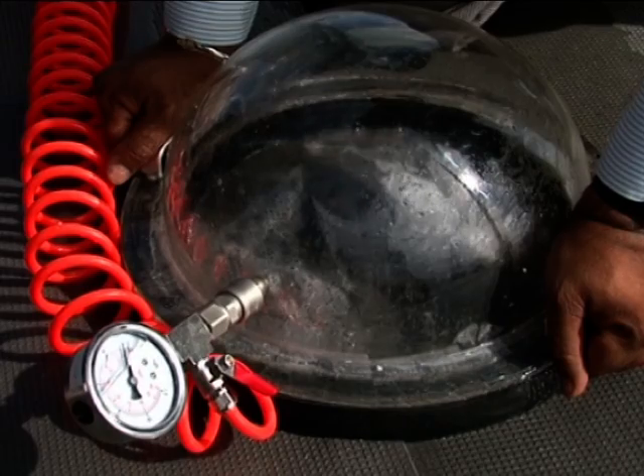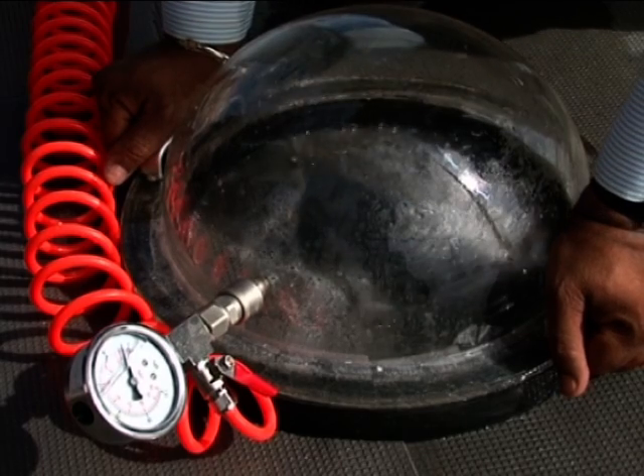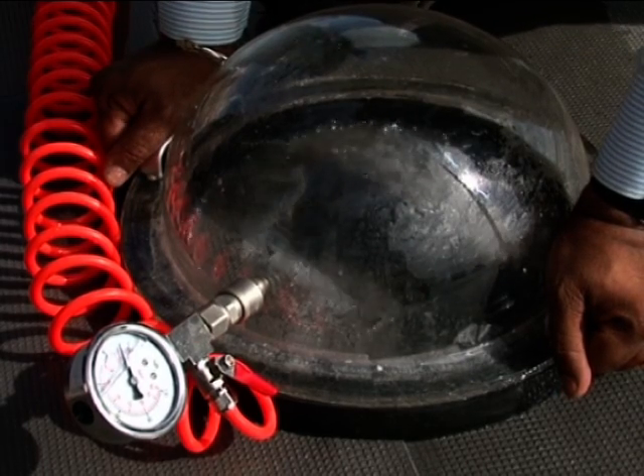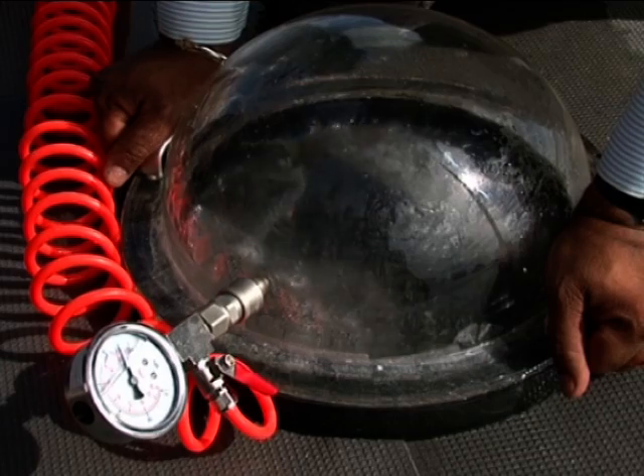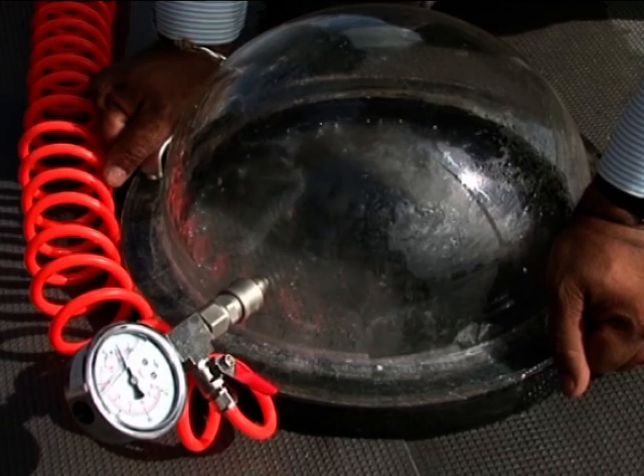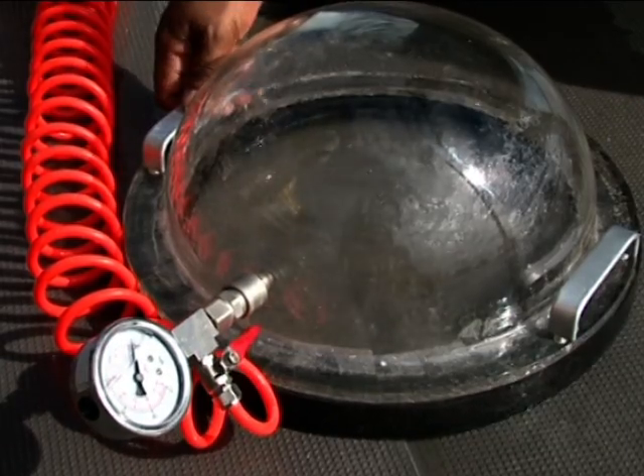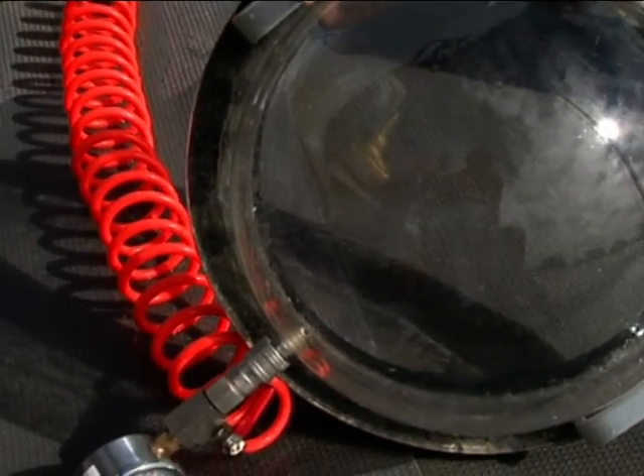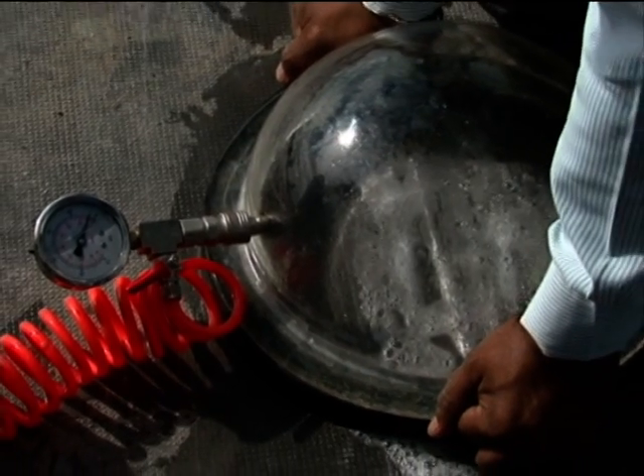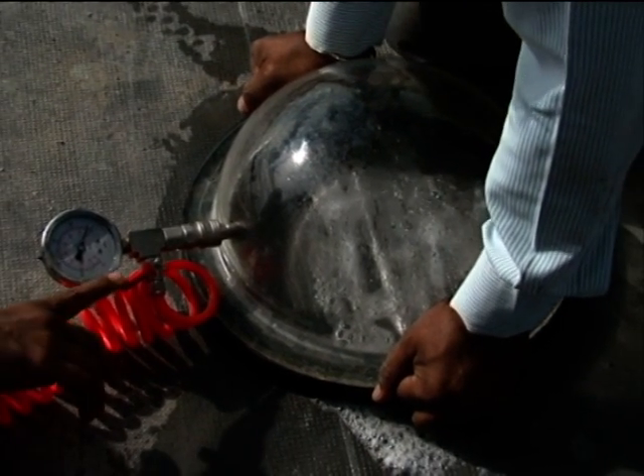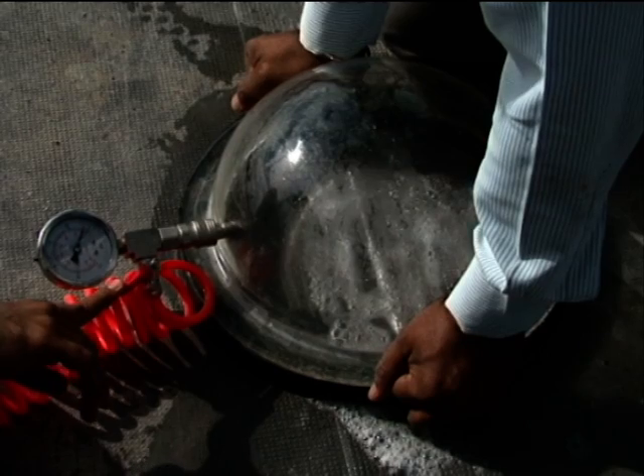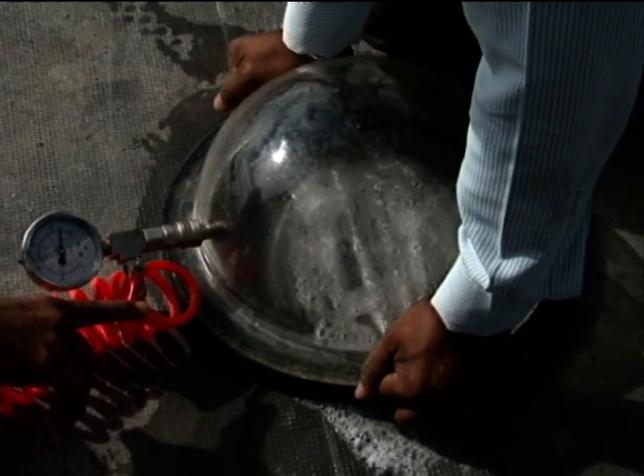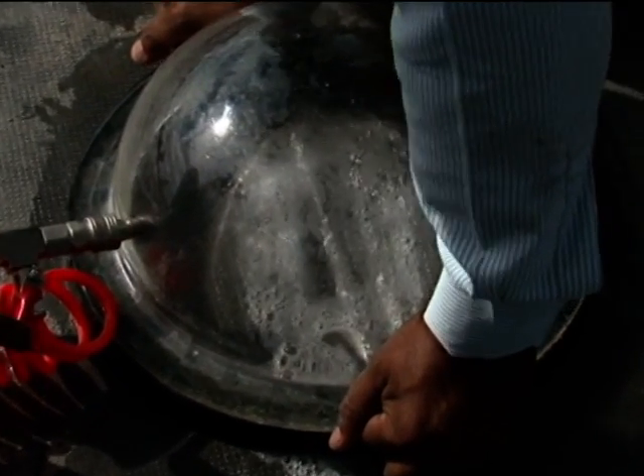Such a condition forces any air trapped below the membrane to rush out through the gaps in the joint area. This rushing out of air creates a series of continuous air bubbles in the foam layer, and the faulty joints are detected and later marked and repaired. Now, under the same condition, if the overlap joints are properly sealed, the vacuum pressure applied will lift the membrane in the glass dome area from the substrate, thus proving its tough nature of sealing.